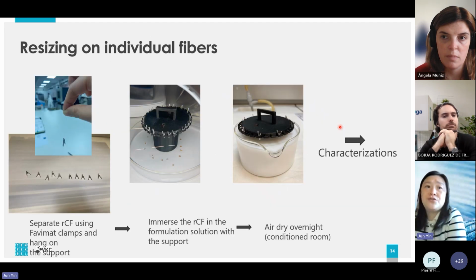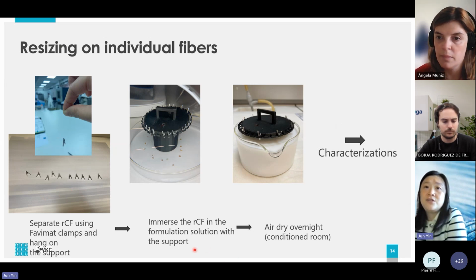Then we try to separate the individual recycled carbon fibers by a Favimat and hang them on a support we developed in our lab. Then we immerse all these fibers into the formulation solutions, dry them in the air overnight, then send them for characterizations.